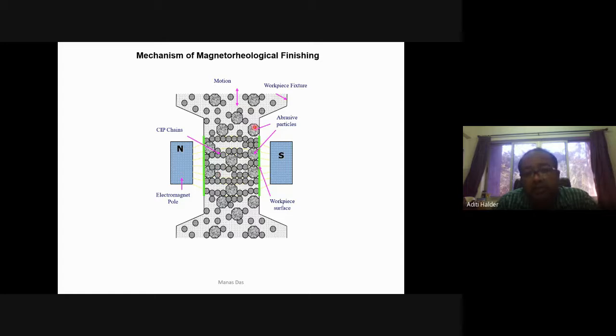Now for preparing this MR polishing fluid, there should be a base media. Base media means you have to mix these abrasive particles and iron particles into a base media. When you are polishing lenses and mirrors made of glass and quartz, you can use a water-based media. Mostly deionized water is used for preparing MR fluid for polishing lenses and mirrors, because deionized water makes a chemical reaction with the surface of the glass or quartz and makes a soft layer over the surface, which can be easily removed by the hard abrasive particles.